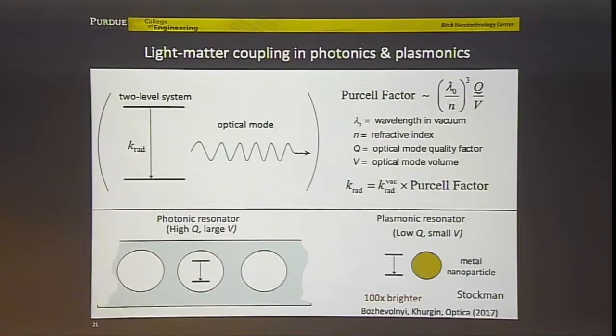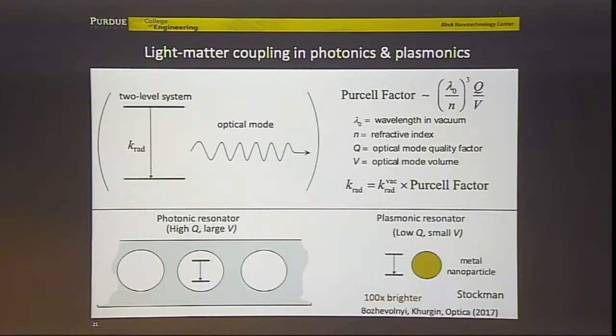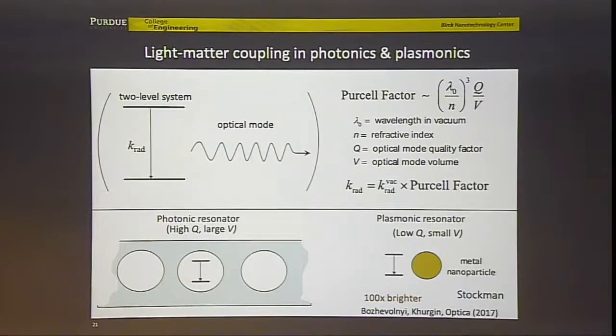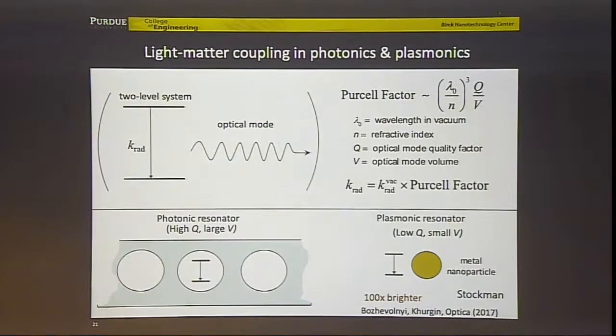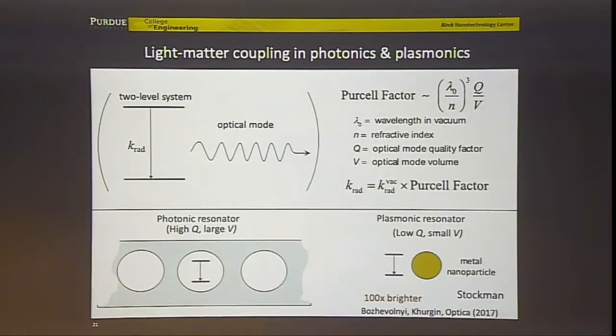And most of the groups, if not all of them, pursue the direction to control this light matter coupling by using dielectric cavities, for example, photonic crystal based cavities, as I mentioned before, with very high Q. And Q could be really high, a million or 100 million, but volume is limited by the diffraction limit, lambda cubed. So you do have dramatic enhancement, but you face the same problem.